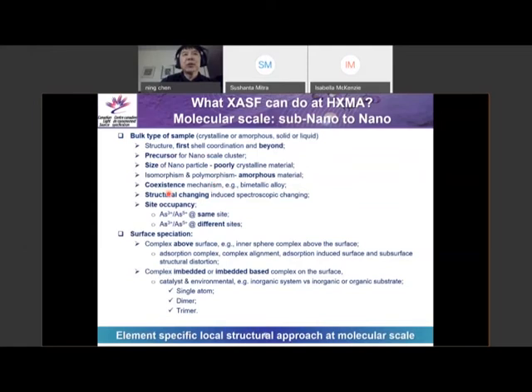And then we can look at the coexisting mechanism of different metallic elements coming together as an alloy. We can look at the structure changing progressively. We can look at the site occupancy in crystalline material: same element, different sites; same element, different oxidation states at different sites. We can look at the surface, for example, an inner sphere complex above the surface. We can look at complex alignment.